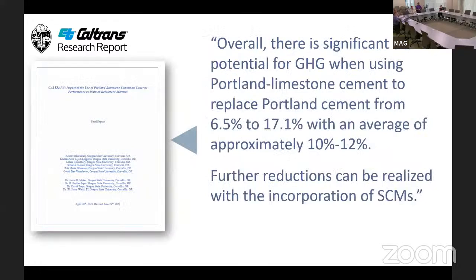One of the final takeaways on the report was, again, when Portland cement is replaced with Portland limestone cement, you get a 10 to 12% average greenhouse gas reduction. And this 10 to 12% greenhouse gas reduction can be further lowered if, say, at a batch plant or a direct job, they're trimming the cement content even lower with further replacement of fly ash or pozzolan or slag.